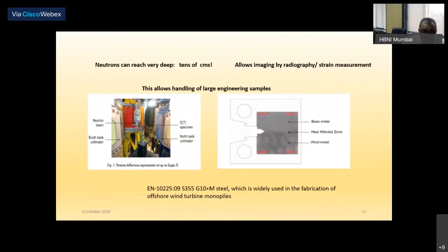So here, in this radiography, portions where the strain, the densities are more, you can do neutron diffraction. And this neutron diffraction is on huge, industrial-size things, not small. Sometimes the job may be as large as, and you can do selective diffraction of small parts of this material and find out the strain after welding, before welding, or after some mechanical processing in the system.